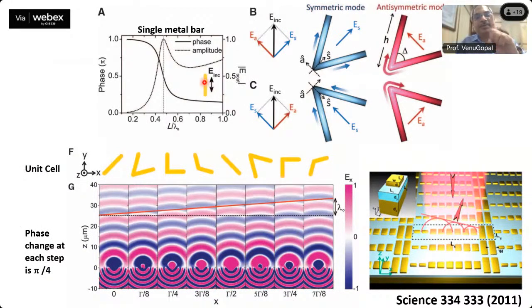If you have a metal rod, you can excite a dipole resonance or higher order multipole resonances. If your electric field is oriented along this direction, you can have a plus and a minus. So a dipole can be excited, or you can have quadrupole and higher order modes. Right. So you have a resonance. This is a dipolar resonance, and there is also a phase associated with it. But if you take two of these rods and align them at an angle, now each one can have a mode, a dipole or higher order mode, and these two modes can couple to each other. This leads to a certain interaction of the coupled modes, with a specific phase relation between them, depending on how these two modes interact with each other and what is the geometrical orientation of these two. So if you're exciting in the S direction, with the electric field along the S direction, then we'll be exciting the symmetric modes.